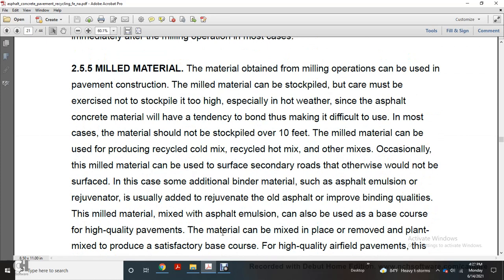Stockpiling requires extra care. The reason not to stockpile too high is that, especially in hot weather, the asphalt concrete material will tend to bond together, making it difficult to use. In most cases, the material should not be stockpiled over 10 feet.